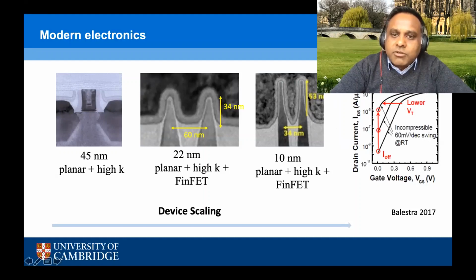To reduce the overall power footprint of this device, we'd like to operate these devices at lower voltages. But that also comes with the consequence of increasing the off-state current. If we decrease the operating voltage of a device by 60 millivolts, we increase the off-state current by an order of magnitude. And this 60 millivolt per decade is called the subthreshold swing. It's also referred to as Boltzmann tyranny.